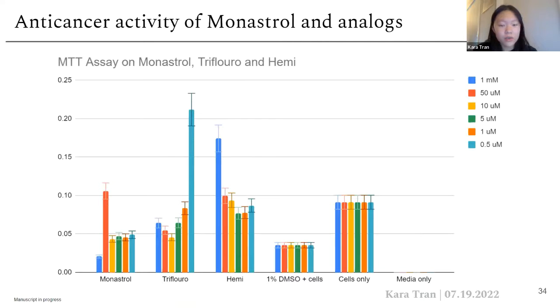And so after we made these analogs, I ran an MTT assay on monastrol and two of its analogs, trifluoro and hemi, and then measured it against a positive control of 1% DMSO in cells. However, against expectations, fluorination seems to have made trifluoromonastrol cytotoxicity slightly worse than monastrol, which is seen in that the absorbances are higher for trifluoromonastrol than monastrol. So we're hoping to explore this in future studies.